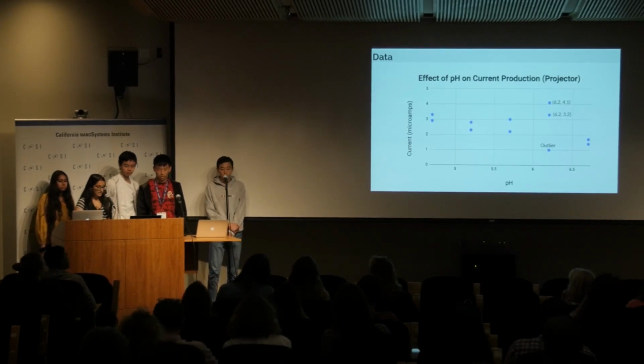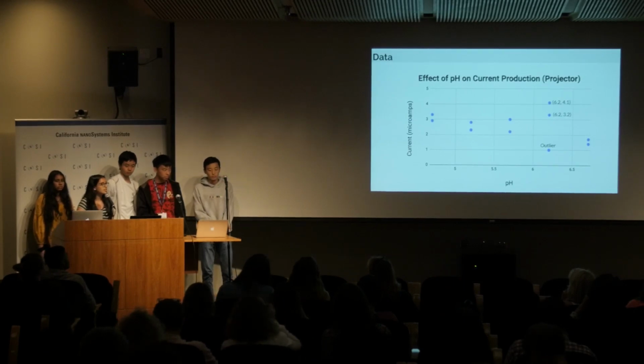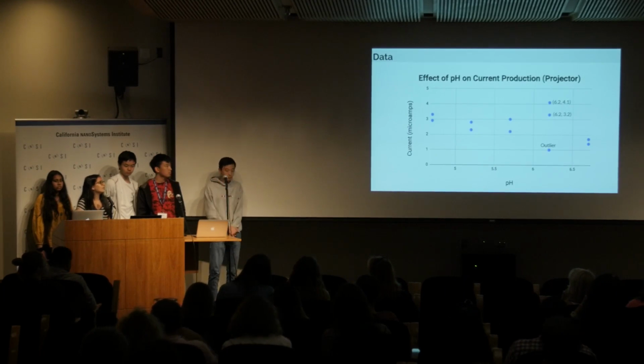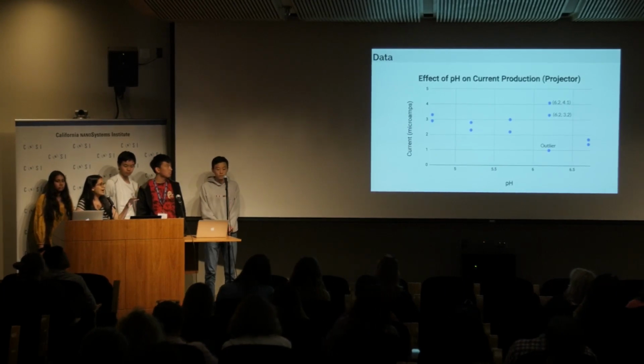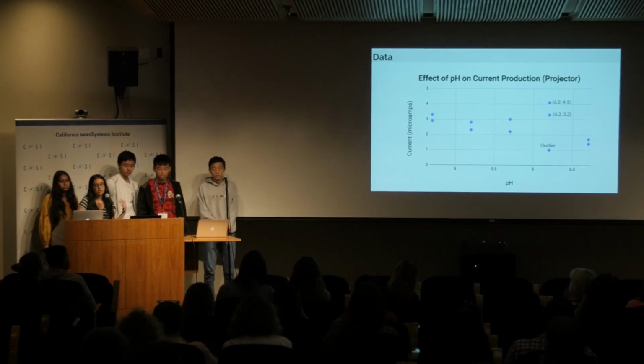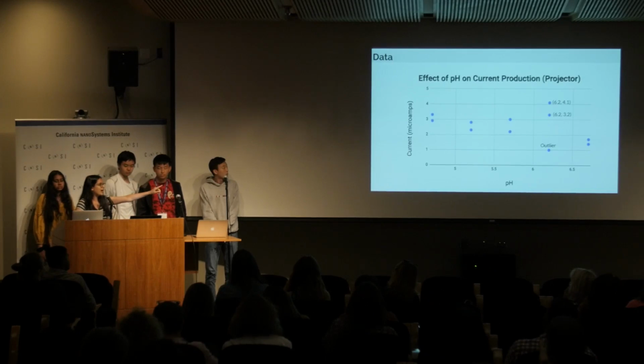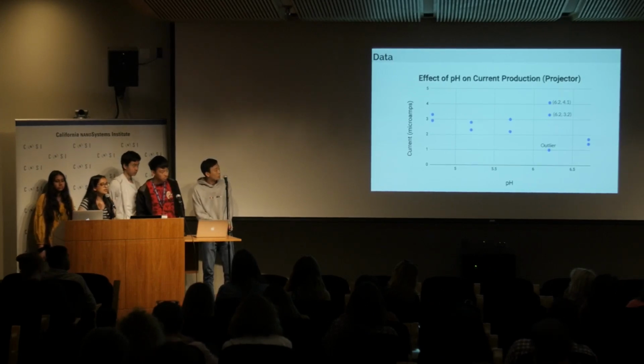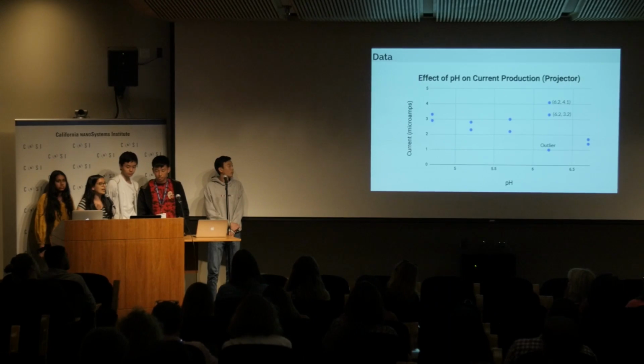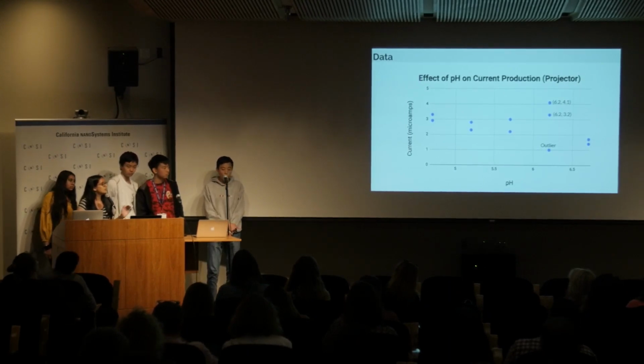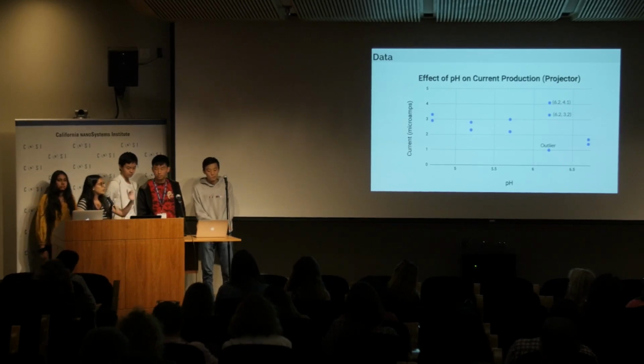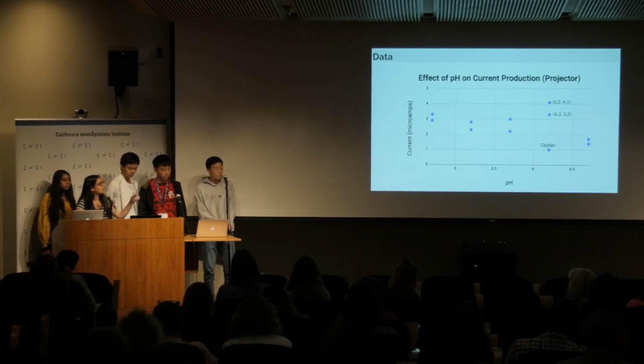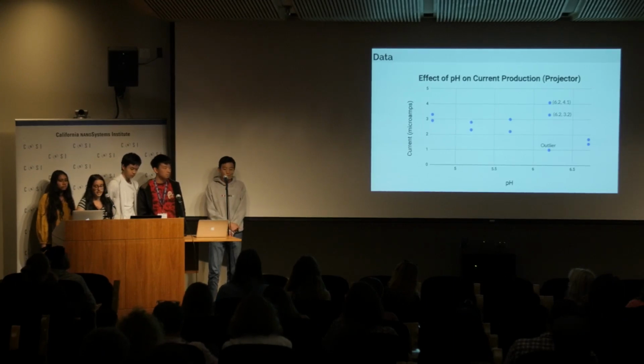And what we found was that there tended to be a more optimal pH, and this happened around the pH of 6.2. As you can see in the graph, at 6.2, our graph seems to have a higher current produced. So in our very first trial, you can see we have an outlier at 6.2. This was because it was the very first solar cell we made, and we weren't as used to making it, and there were some errors that happened. But when we did it for the second and third trial, we found that results greatly increased, and this is because 6.2 was the optimal pH.